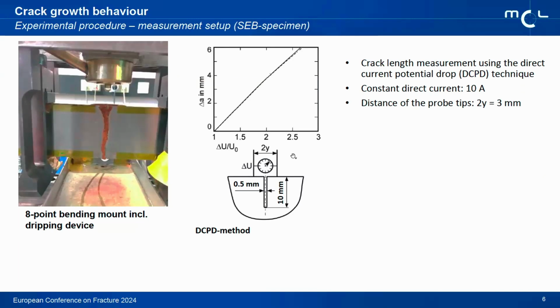Okay, to investigate now the influence of the corrosive environment, we built such a dripping device where a corrosive fluid was dripped onto the specimen above the notch. So approximately every 2 seconds, the fluid was dropped onto the notch root. And we measured the crack length via the direct current potential drop technique with a constant current of 10 amperes. And the distance of the probe tips to measure the potential drop was 3 millimeters. So that's the measurement setup.